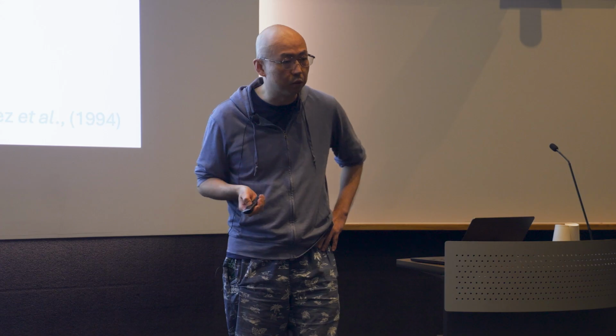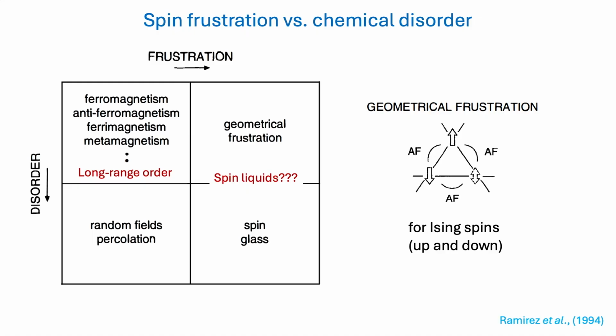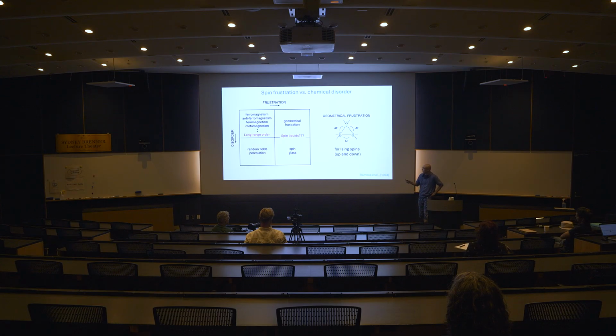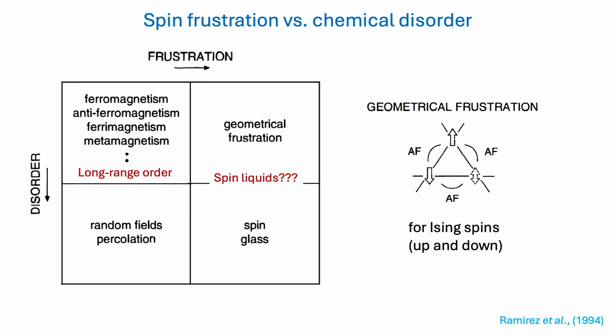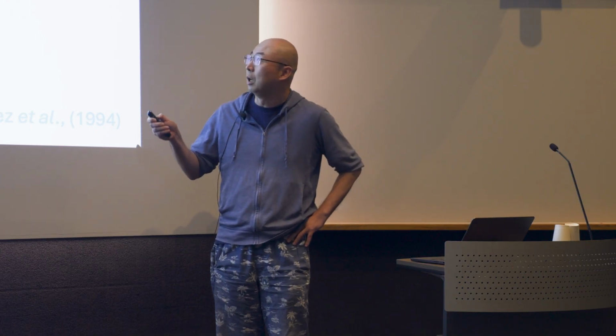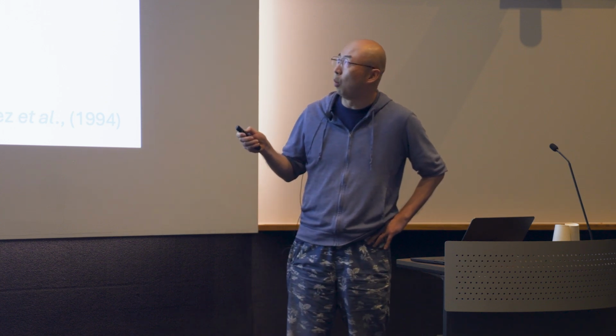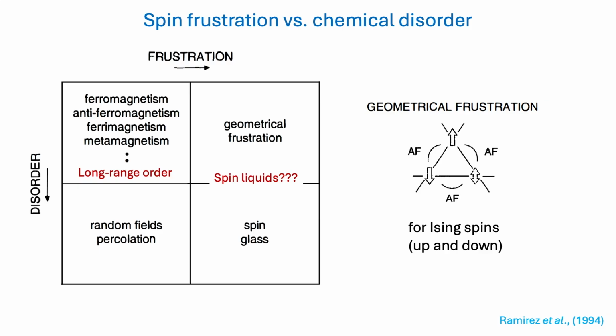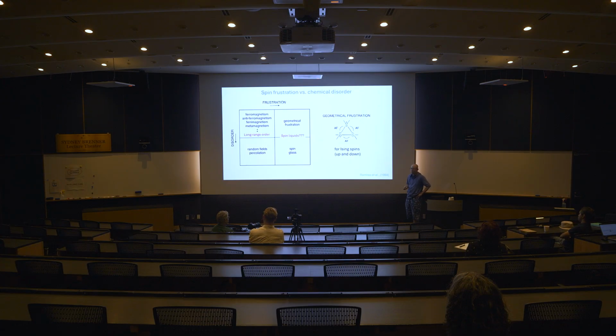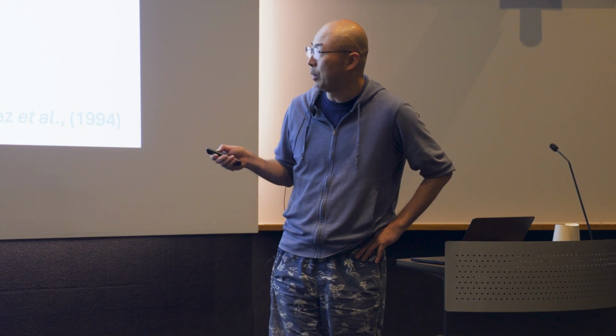So that's for the charge system. For the spin system, we have a certain understanding about this behavior. We know that there are spin frustration and chemical disorder. Spin frustration is actually a very simple concept to understand. You can think about a triangular lattice with 3 spins on the corners, and each can only have up or down choices. And they interact antiferromagnetically, meaning that neighboring spins prefer to align in opposite directions. Now you can see for the top one, if it's pointing up and this one pointing down, then this spin becomes very awkward. It doesn't know whether it's pointing up or down. So this is called spin frustration. And this is purely based on the geometry of the system.